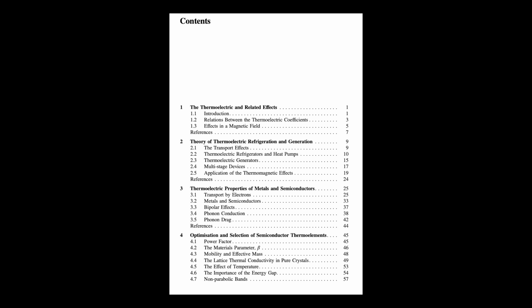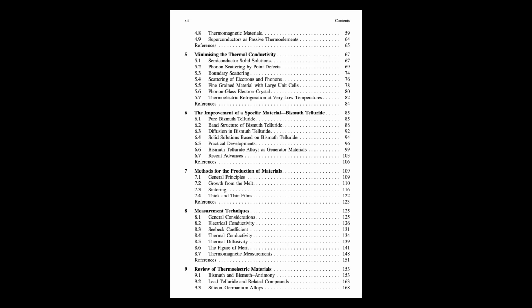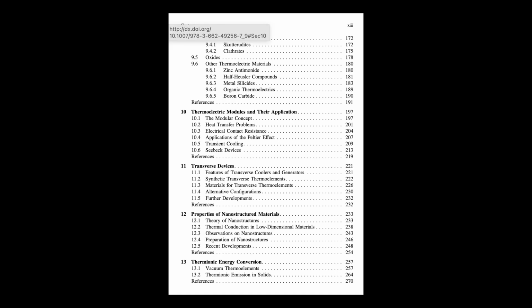What about the Seebeck coefficient? How's that done? For Seebeck, you need a known, stable temperature difference across your sample. Then you measure the voltage it produces. You might attach tiny thermocouples right to the sample to measure T at both ends, plus the voltage, or have the sample between a heater and cooler block, measure the block temps, and infer the sample gradient. The author notes that if the sample has low thermal conductivity, most of the temperature drop is in the sample, even with good block contact. But sample uniformity matters. How you make electrical contact matters.